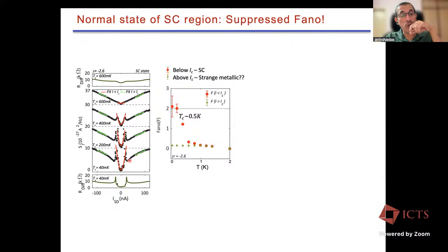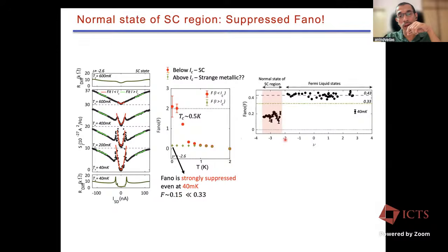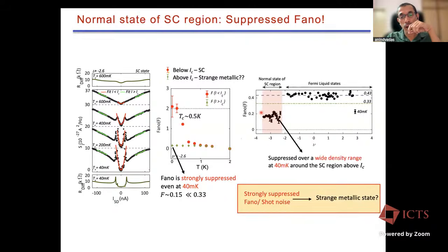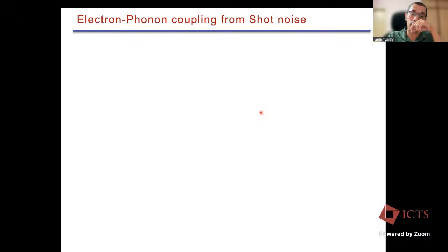Most importantly, in the normal state above the critical current, if you look at this Fano factor, which we expect to be the Fermi liquid regime 0.43, we see much more suppressed Fano, which is close to 0.15. And if you summarize the Fano of the normal state around the superconducting dome and the Fano of the normal state, which I am calling a Fermi liquid state, you can see the Fano is quite suppressed around the superconductivity regime. So the question is, why these suppressions? Is it a strange metal or is it electron phonon coupling?